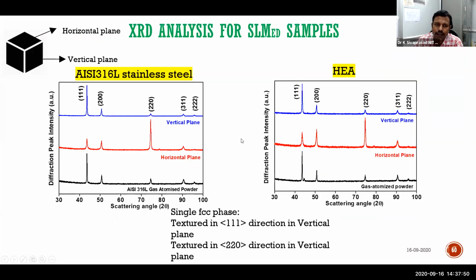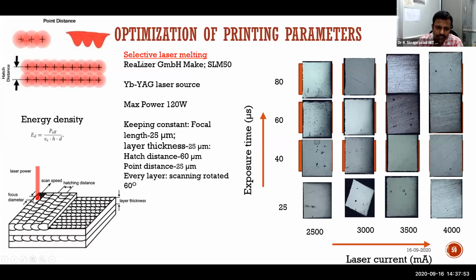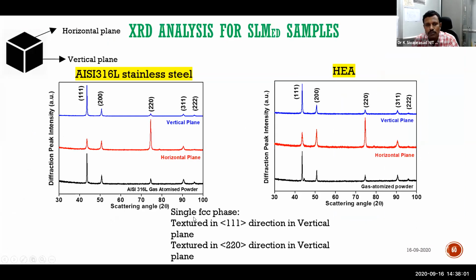Then we have done the vertical plane because the building plane will be like this. This is the horizontal plane and this is the vertical plane. One has to study the vertical and horizontal plane orientation because the grain orientation will change from top to bottom side. So vertical plane gives one orientation and horizontal plane another orientation. Always the vertical plane matches with that of the other elemental powder systems. That's what we have seen. Vertical plane peak intensity variations are matching with that of the atomized powder. Similarly, atomized powder of high entropy alloy and the vertical plane of high entropy alloy match. Horizontal plane texture will vary. This is because of the texture associated with any additive manufacturing components.